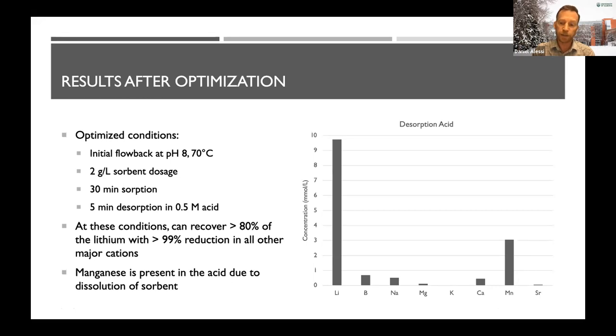And what this shows you is that somehow in this material, manganese is being lost. And that's not good because, again, you want to reuse this thing 100 times. Well, you don't want the sorbent itself being chemically dissolved, essentially, right? So recovery is always over 80%. Typically, really, we see 90 to 95% recovery, sometimes even approaching 100%. And again, we've reduced 99.9% of the other cations in solution. So the problem to solve here is the manganese issue because that indicates loss or dissolution of the sorbent.